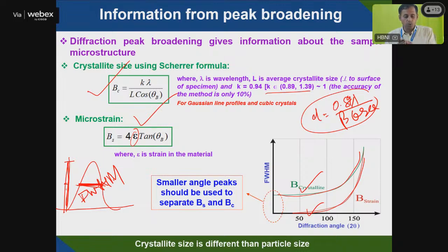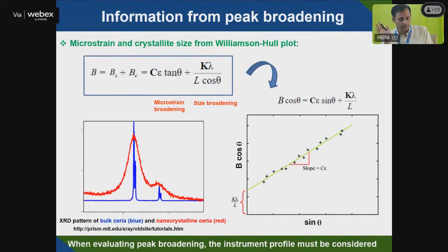You can get it, but in the whole formula you are assuming your particle is spherical. And this equation, the Scherrer equation, is only valid when the particle is considered spherical, and it can't be valid for bigger particles. If the particle is more than 100 nanometer, your Scherrer equation is not valid. So you can't use the Scherrer equation for bulk crystallite size calculation.